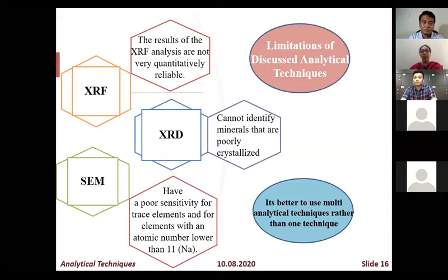These three techniques have some limitations also. Like XRF, the result cannot be fully quantified because it's a surface analysis. And XRD sometimes cannot identify minerals that are poorly crystallized. And SEM has a poor sensitivity for trace elements, which means that if any element has a lower atomic number than 11, we cannot detect it through the SEM analysis.